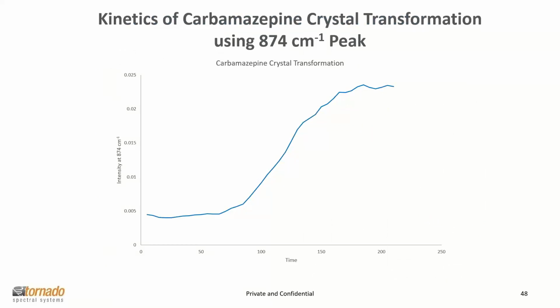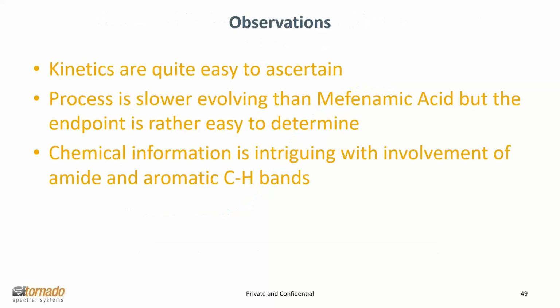And again, if you're interested in a simple trend plot, we can use, for example, that peak at 874 wave numbers to look at the crystal transformation as it's taking place to get a better indication of the kinetics of the process. So the observations here, again, the kinetics are quite easy to ascertain. This process is slower evolving compared to the mefenamic acid, but again, the endpoint's rather easy to determine. And the chemical information that you get is intriguing with the involvement, for example, of the amide band and the aromatic CH band. So again, relating that molecular information back to something like the additional data that you would get with X-ray, for example, could be very interesting.